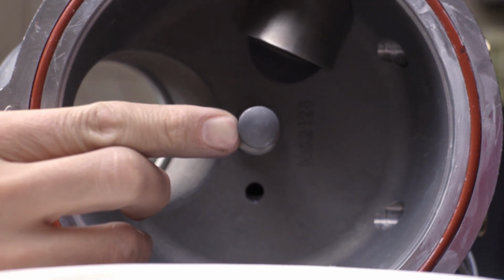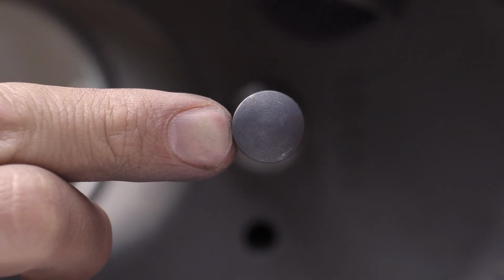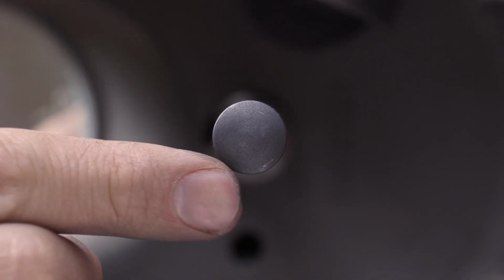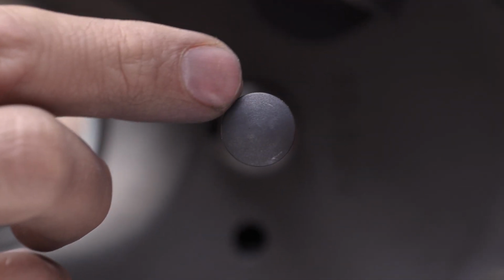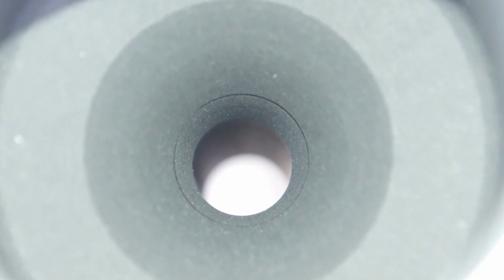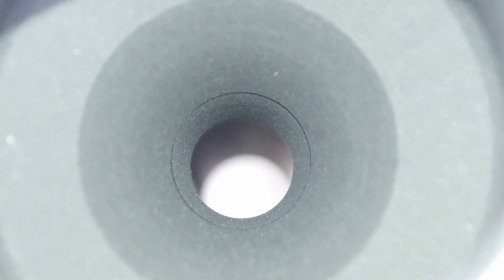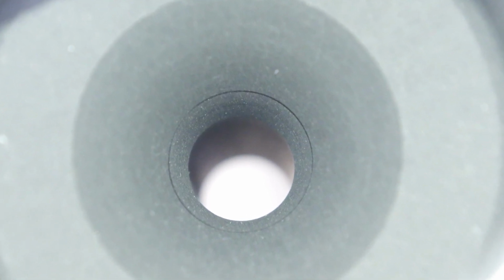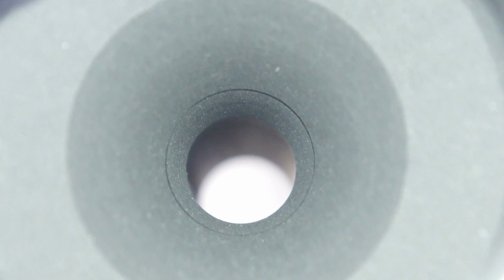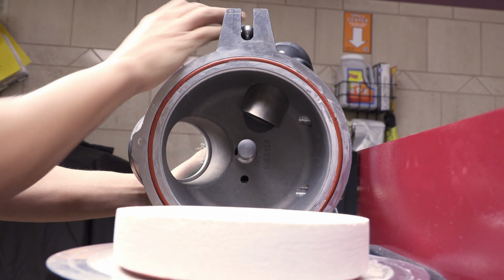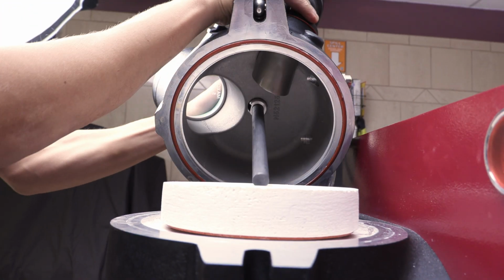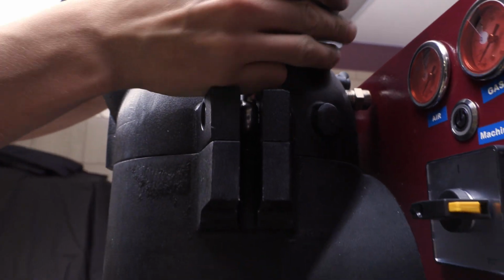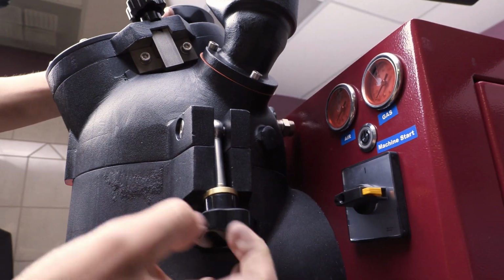We should see a full shiny ring on both. If there is a break in the shiny ring in either of these components, you should replace it because that means there is a gap that will allow molten metal to flow prematurely and drip into your flask, causing no-fills. These consumables are new, so they should not have a problem with sealing, but it's always good to check. Now we can close the hood and we are ready to cast.